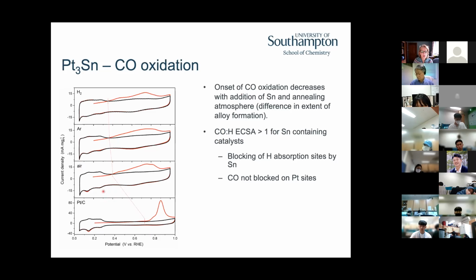It's interesting that we can measure the electrochemical active area by the area under these peaks, or the area associated with the hydrogen adsorption or desorption peaks in the CV, right? And we can see that for the tin-containing catalysts, the CO area is greater than that of the hydrogen area. And this suggests that there's some tin on the surface of these particles that may be blocking the hydrogen adsorption sites, but the CO sites are not blocked. Okay, so that's interesting.